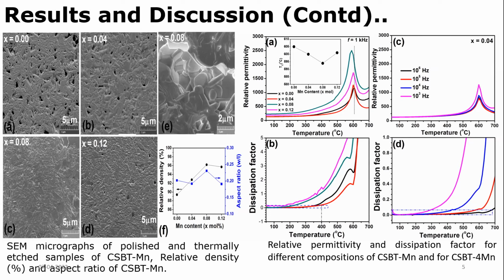Furthermore, in the B diagram, you can see the dissipation factor, and with temperature the dissipation factor usually is constant up to 400 degrees Celsius, which tells us that we can get good piezoelectric properties. And in the C diagram, this is basically for the 0.04 concentration, and below you can see the dissipation factor, which proves that the dissipation factor is low, loss is low. So this is a good composition.